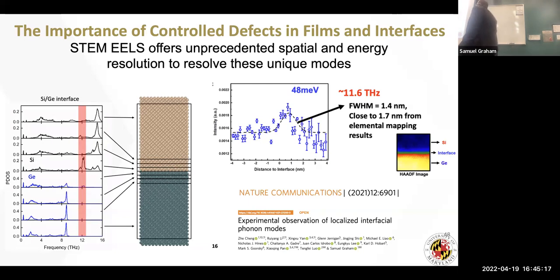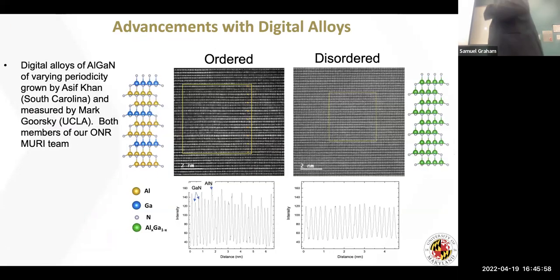And so what we were able to do was use a TEM with STEM EELS, electron energy loss spectroscopy. So we're able to measure these vibrational modes, and we're able to confirm that right here. So this is the interface. One nanometer away from the interface, on the silicon side of the interface, you are seeing a peak at 48 meV, which is 11.6 terahertz. And the calculations were showing somewhere right around 12. So for experiments versus calculations using a neural network potential, that's actually pretty close. And it's showing it's biased to one side of the interface and not the other. So it shows that these interfacial modes can exist.